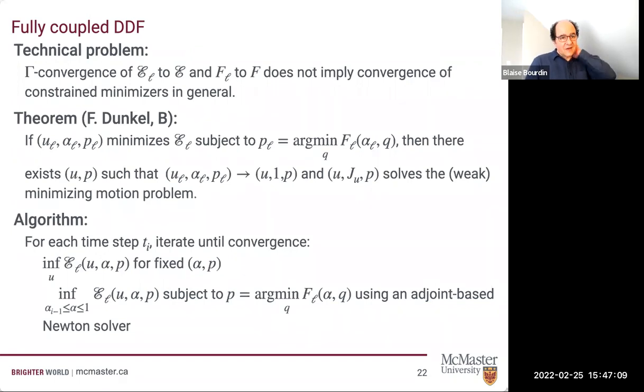Something we didn't really think first, and we're not the only one. Lots of people in this business are looking at this two-level optimization problem and just approximate each level separately and don't try to show convergence. So it turns out that for this example, essentially we can show some form of compatibility in the gamma convergence. Without going into the technical detail, we can use the same recovery sequence for both problems. And so we're actually able to show convergence of minimizers, of solutions of the constrained minimization problem.